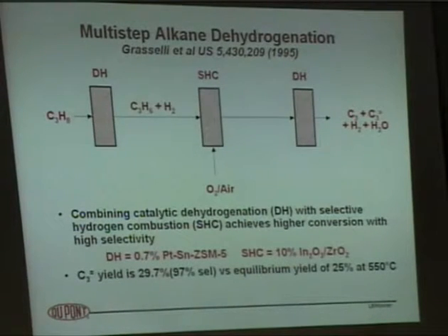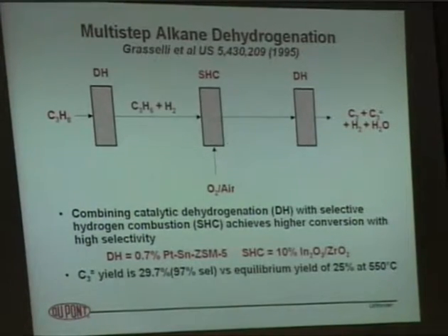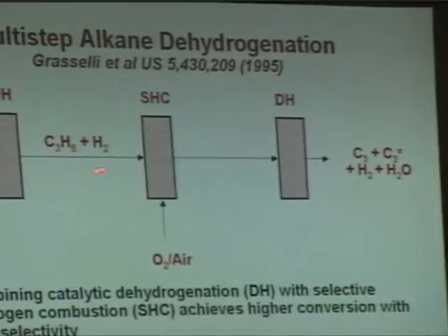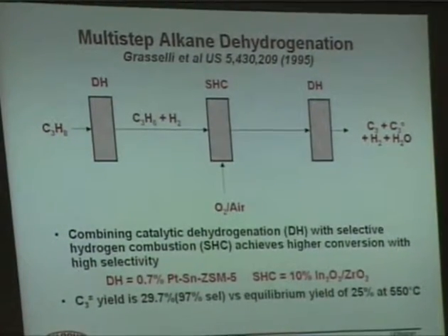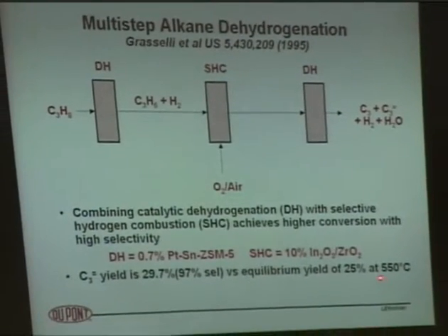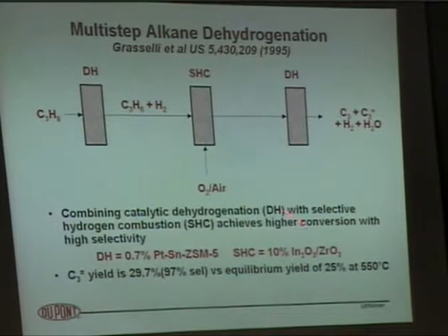Well, Bob Grasselli has a patent from when he was at Mobil on an interesting way to do oxidative dehydrogenations. And the idea there is to shift the equilibrium. So we're taking a hydrocarbon like propane to propylene plus hydrogen. It's an equilibrium limited reaction, requires energy to drive that reaction, and the conversion is limited at 550 to, let's see, 25% equilibrium conversion. What Bob suggested was to put in series here what he called a selective hydrogen combustion catalyst system. So he would run the first reaction using a platinum tin ZSM5 type catalyst, standard dehydrogenation catalyst, but then in the second reactor he would take this effluent, selectively oxidize the hydrogen. Don't touch the propylene, don't touch the propane, selectively oxidize the hydrogen.